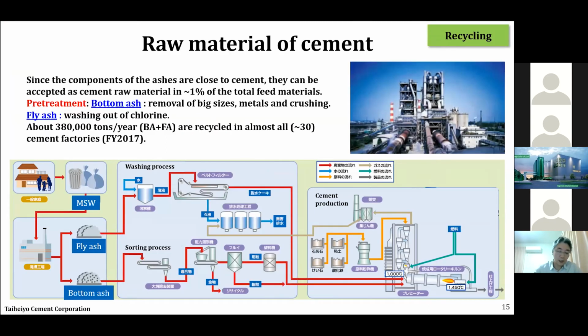And in this slide, I will explain the recycling of ashes as raw material of cement. Since the components of the ashes are close to cement, they can be accepted as cement raw material. However, ashes contain elements that are disliked by cement, such as chlorine and chromium, so only about 1% of the total feed materials can be substituted by ashes.